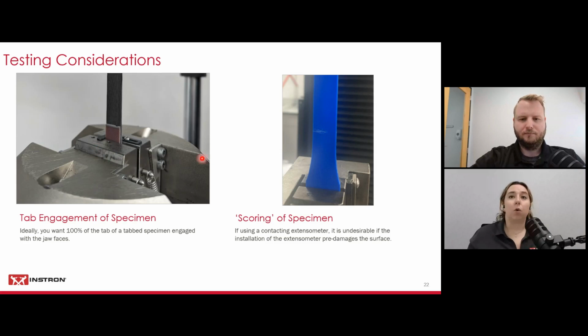And then lastly, scoring of a specimen. If you are using a contacting extensometer, it's undesirable if that installation pre-damages the surface. Now, this is a plastic dog bone. Typically, we see this happening in softer materials such as plastics, elastomers. I didn't happen to have any issues with this during my testing as my specimens were robust enough, but you just want to be aware if you have a softer material or maybe a ceramic type of composite, you don't want to pre-damage the specimen before you've even started testing.